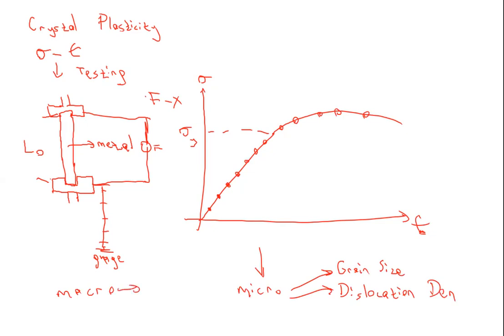For macroscopic features, we just displace the material, we pull it till fracture, and the input parameters are temperature, which is one parameter, and strain rate, which is constant during the tensile test, another parameter. Of course, we have instant displacement as a function of time. And this strain rate represents how quickly we are stretching the material. The strain rate is dL over L0 dt, with the initial length L0. So this is the experimental condition.